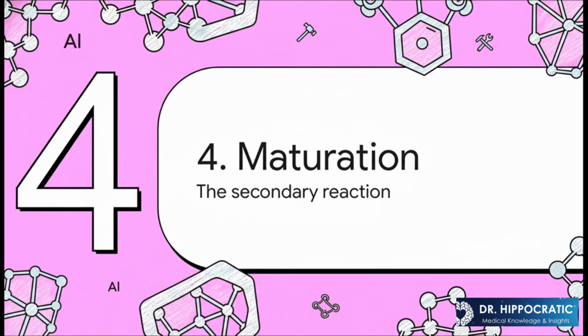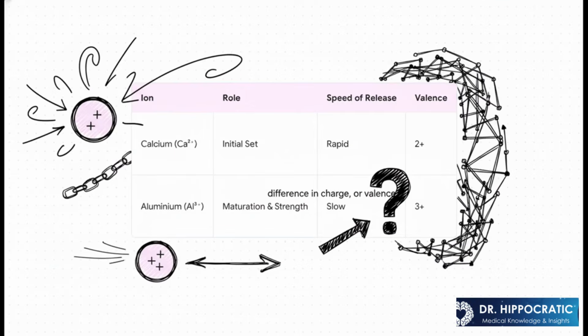Which brings us perfectly to the second, much slower part of the reaction, which is called maturation. This is where the material really develops its final strength and toughness, and it's all thanks to our other key player, aluminum. This table really breaks down the difference between our two main ions. You've got calcium with its 2+ charge, which is released super fast to get the party started and form that initial set. But then you've got aluminum. It's released much more slowly, and this is the key, it has a 3+ charge.